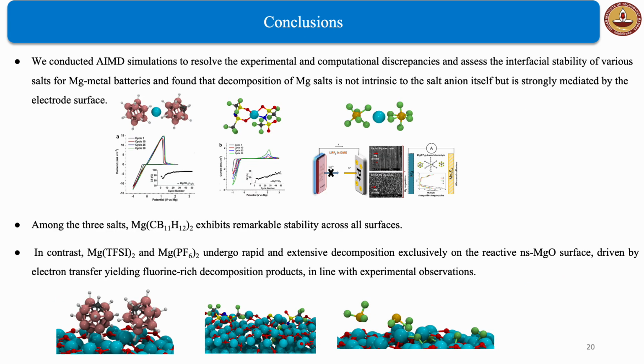Moving on to the conclusions, we conducted AIMD simulations in this work to resolve the various experimental and computational discrepancies and assess the interfacial stability of different salts for magnesium metal batteries, and found that the decomposition of magnesium salts is not intrinsic to the salt anion itself but is strongly mediated by the electrode surface. We found that the magnesium carborane salts exhibit remarkable stability across all electrode surfaces, whereas the MgTFSI and MgPF6 salts undergo rapid decomposition exclusively on the reactive ns-MgO surface, driven by electron transfer from the surface, yielding fluorine-rich decomposition products in line with the experimental observations.